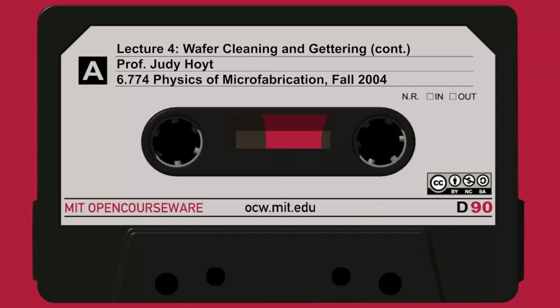Bin 1 is any particle that is between something like 0.2 microns and 0.3 microns. In that size range, it found 16 particles. In fact, the system only found 21 on the entire wafer. So there aren't very many particles on this wafer. It's pretty clean.